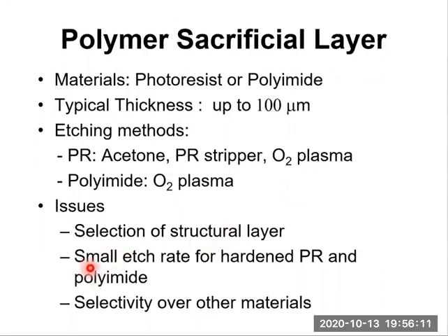Second, small etch rate for hardened PR and polyimide. Hardened PR and polyimide are typically etched by oxygen plasma, which is relatively slow. So it may take a very long time to finish the sacrificial etching. The selectivity over other materials.